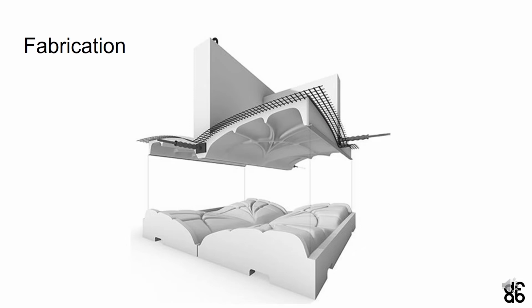In our prototypes, we consider the fabrication of the slab in discrete nodes with area of around 1 square meter, centered on the intersection of 2 ribs. The height of the slab can be adapted by the concrete printing process and depends on the span of the slab. The interstitial field is a thin shell with a thickness of only 2 to 3 centimeters that integrates a carbon fiber mesh reinforcement for stiffness and for mitigating shrinkage cracks.